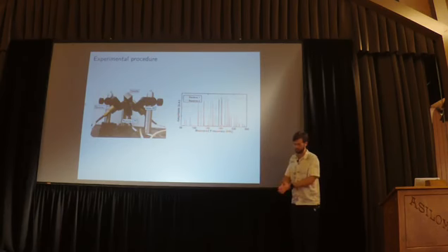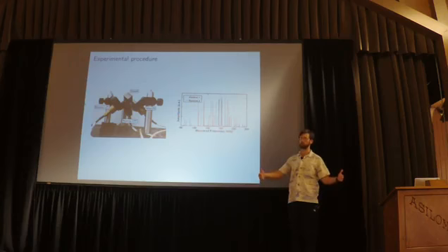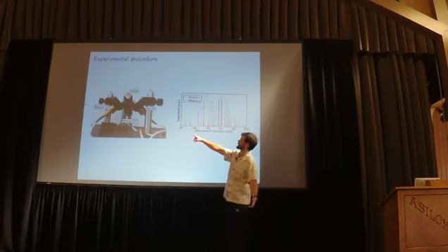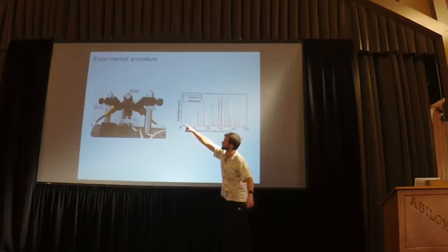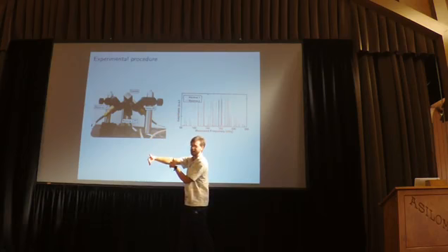The key thing here is that where the sample resonates is going to be a function of its geometry, and it's going to be a function of these elastic constants. We know the geometry, we want to figure out the elastic constants, and that's a typical experimental setup for this. That cube right there is not big. There aren't little people here. It's maybe this high on a desk.